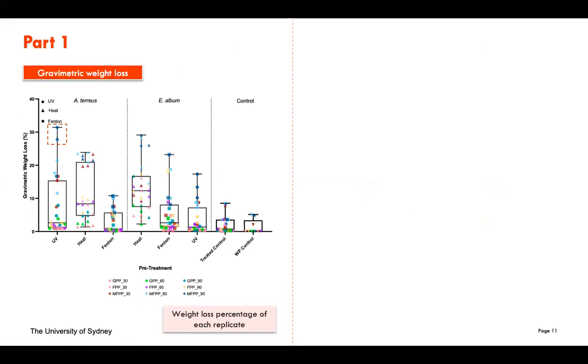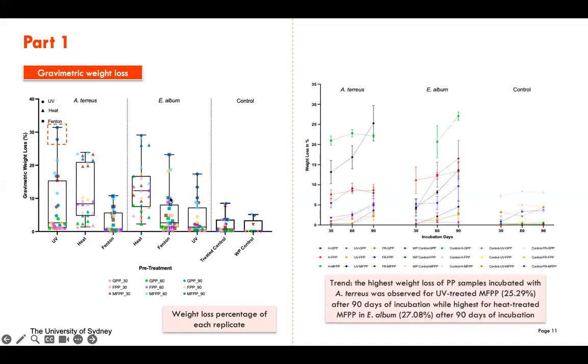Right. So the next one, we also did a gravimetric weight loss. This is basically just weighing the polymer before and after, and then we see the differences, like how much of this polymer has been consumed or degraded by the fungi. Okay, so same goes with the fungal biomass data that we saw earlier. We see that the highest weight loss was also produced by Aspergillus terreus compared to Engyodontium album. And the same thing, the trend shows that the highest weight loss of polypropylene are incubated with both UV and heat-treated metallized film. So these two have been shown to cause the most weight loss, and we could conclude that these fungi are able to feed on this metallized film compared to film and also granulated film.